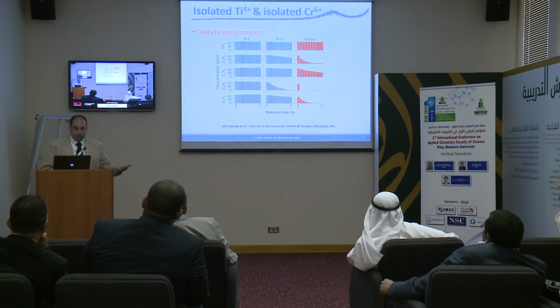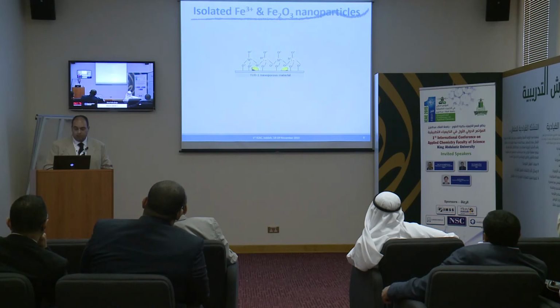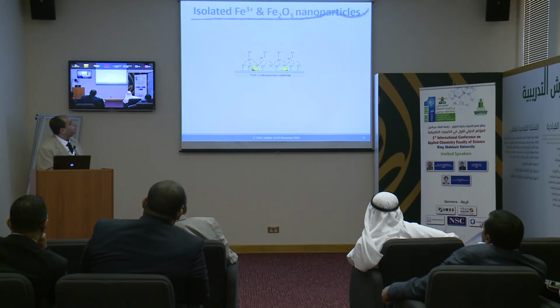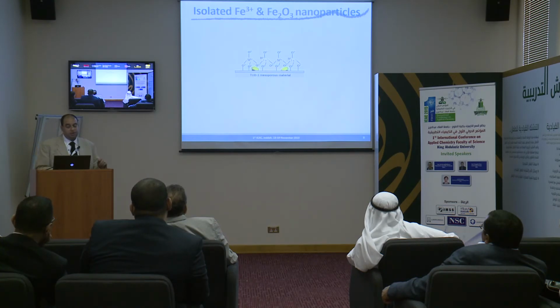So that was the first example, and as I said, this is the very traditional example to shift the absorption spectra of titanium to the visible light region. Well, let's go to the traditional catalytic examples. Here we have a system consisting of Fe3+ isolated active sites, plus we also have some iron oxide as nanoparticles embedded in the TUD mesoporous structure.